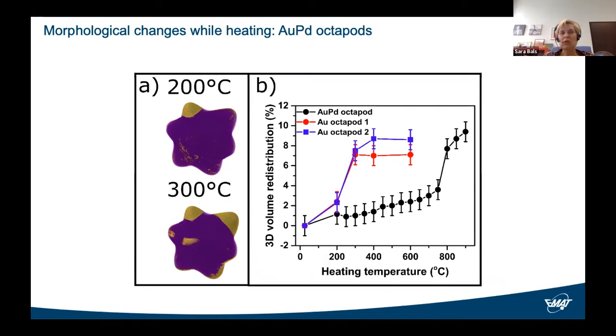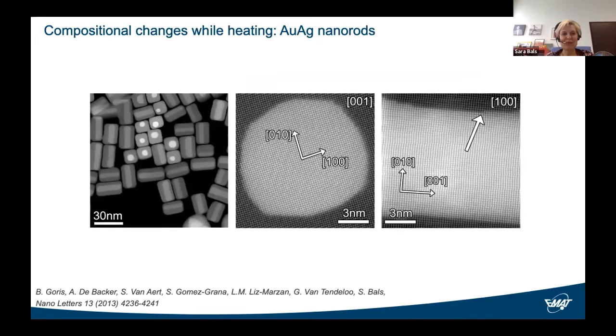Now, these materials also made us wonder, could we do the same type of experiments as I showed you in the introduction of the talk, where we would map the chemical distribution in bimetallic nanoparticles? And the system that we chose to perform these investigations is this one here, gold, silver nanorods. And these images are acquired using what is called high-angle annular dark field scanning transmission electron microscopy. Main idea is that the intensity in the images scales with the atomic number Z squared, more or less. So that is why the gold in the core appears with higher intensity in comparison to the silver in the shell.